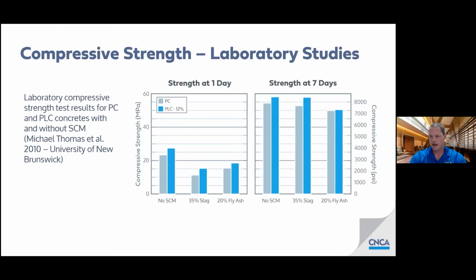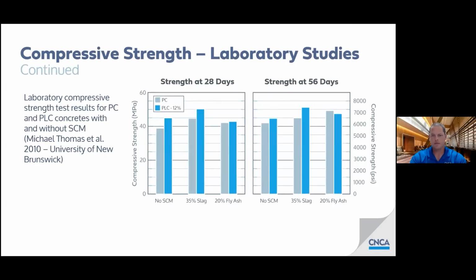And you can see in the case of strength at 1 day and 7 days, the Portland Limestone Cement was coming out a little bit ahead of the Portland Cement. When we look at the same mixes at 28 and 56 days, we see much the same, although it appears that the ordinary Portland Cement caught up a little bit and maybe past that fly ash, 20% fly ash at 56 days. But again, the theme is very comparable performance because this is formulated to be a 1-to-1 replacement.